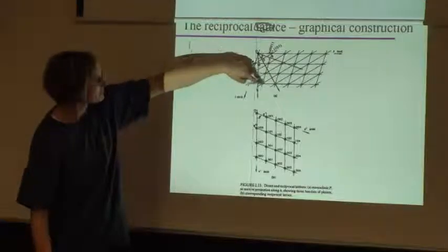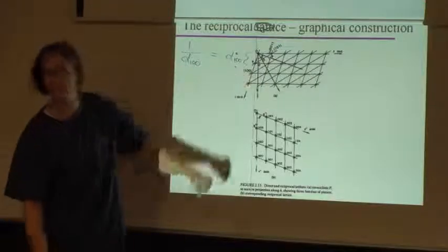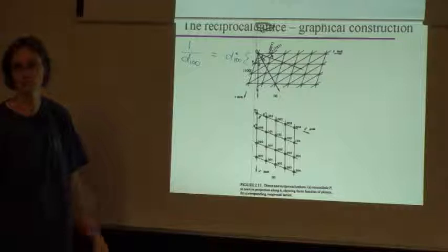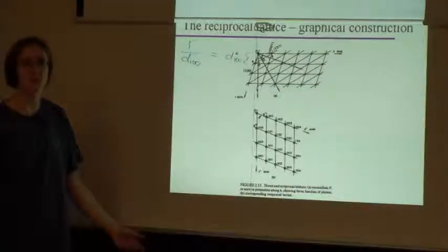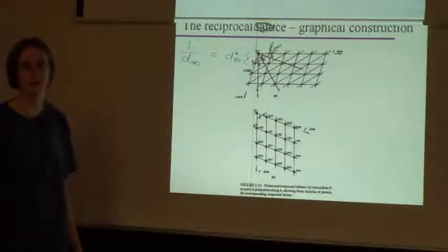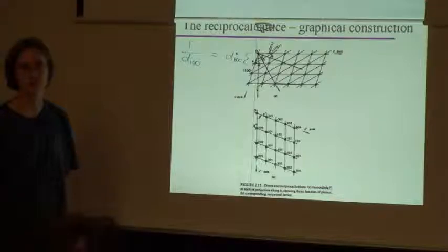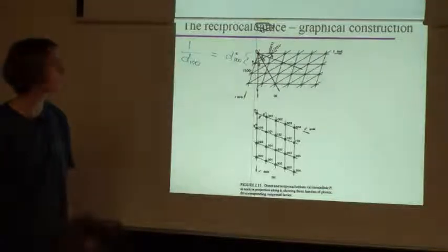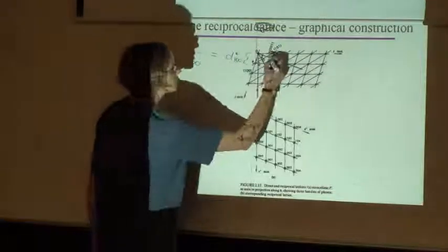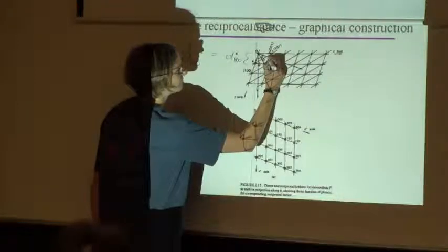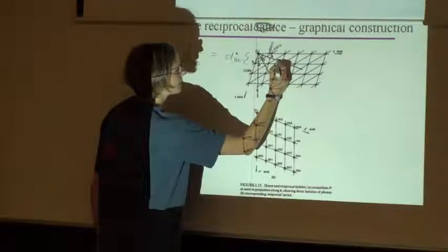This spacing seems to be a little bit bigger than that one, right? So given that we said the other one, maybe it was 1, let's make it 1.5 or 3/2. What distance do I need to mark points now? 2/3. So it might be something like this.